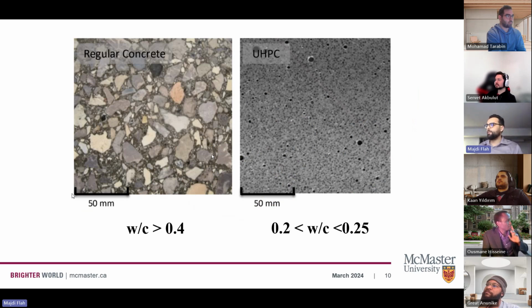This is a representation of how regular concrete particles look and how UHPC looks. As you can see, for the normal strength concrete, we have a lot of coarse aggregates and we have a lot of voids between them, for a water cement ratio that usually starts at 0.4. For UHPC, it's a highly dense matrix, and usually the water cement ratio is between 0.2 and 0.25.